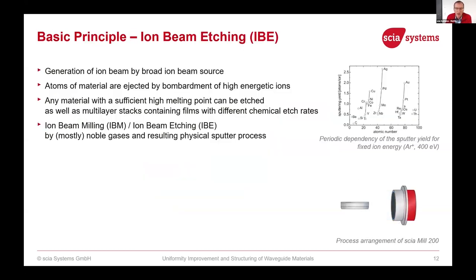Ion beam etching is similar to the trimming, but here we irradiate the full wafer at once with an ion beam source. The ion beam source is accelerating ions to the surface, and on the surface, the material is sputtered out, is removed, like it is shown here in this diagram in the upper right corner. And we can etch nearly any material as long as it has a sufficiently high melting point and is vacuum suitable. Even multi-layer stacks can be easily etched, since the physical etch rate is more or less in the same order of magnitude for all materials.